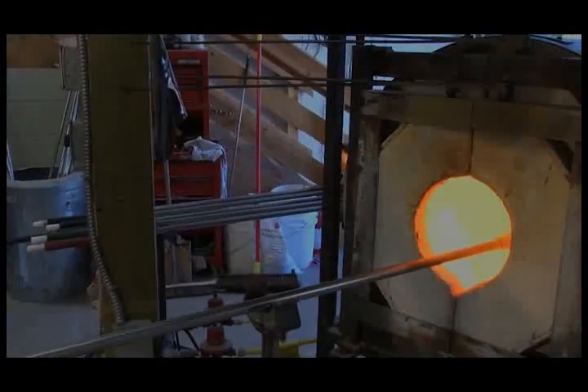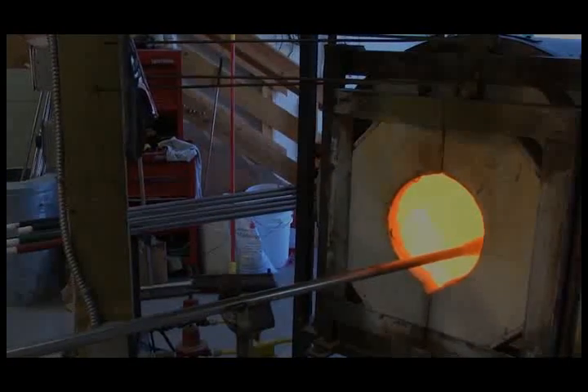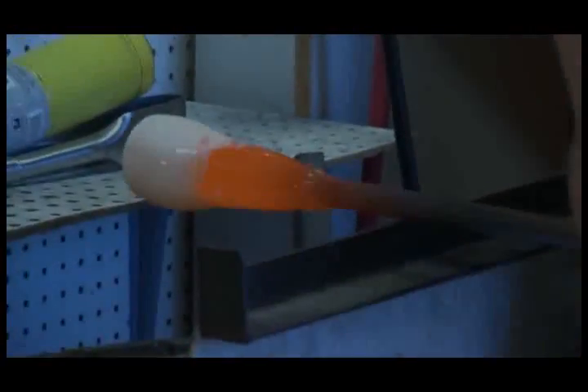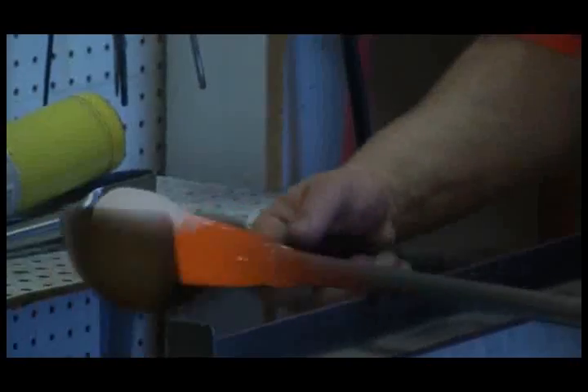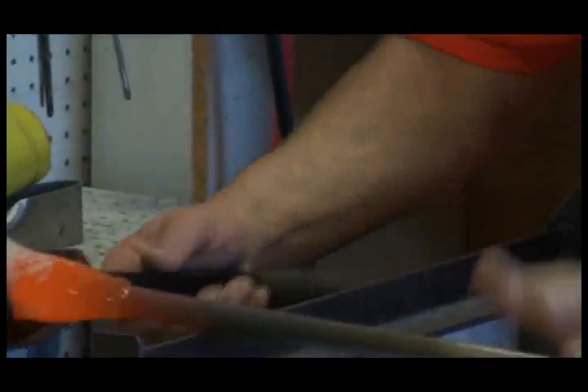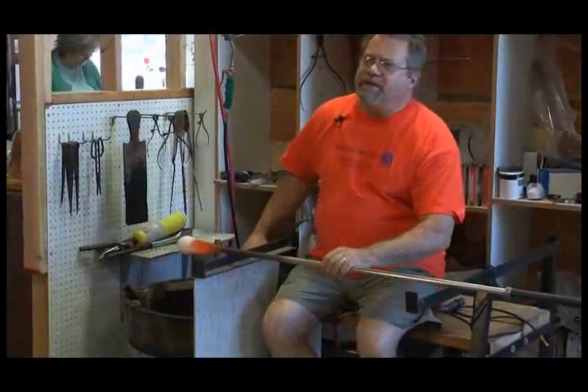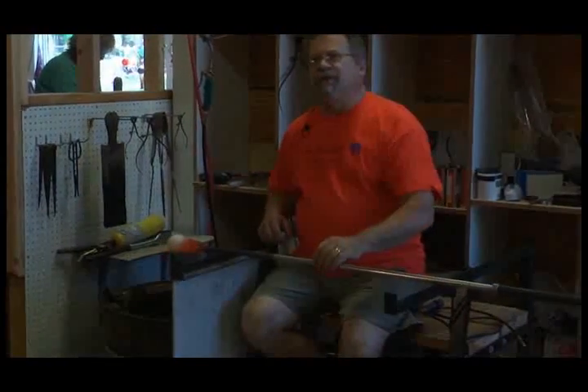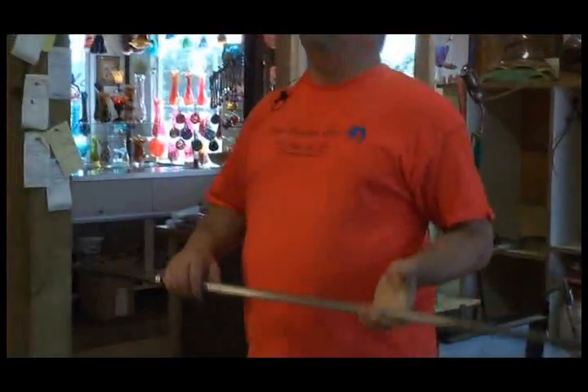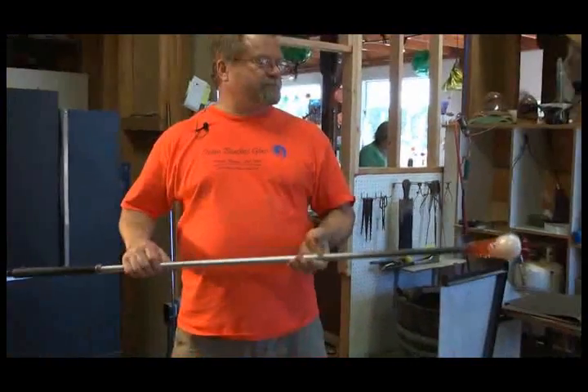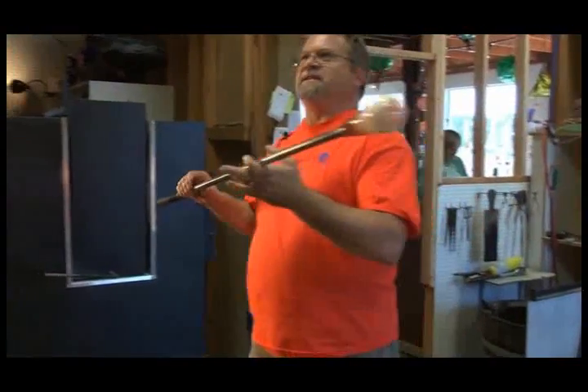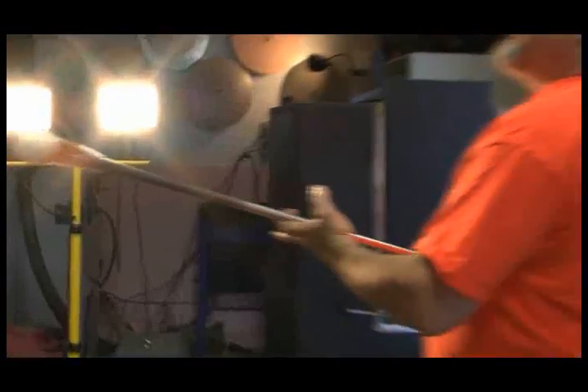Then it's back to the glory hole to once again bring the glass up to its working temperature. And over here at the bench, I'll shape it with one of the blocks. So now I have to let this cool down to about 1,100 or 1,200 degrees so that it's stiff enough to support the weight and the heat of the next layer of glass. And you can actually see a little pink coming in at this point, and quite a bit of pink for some reason on the bottom.